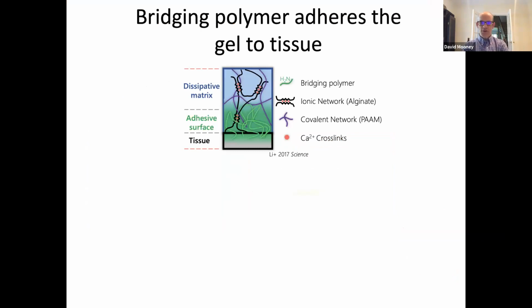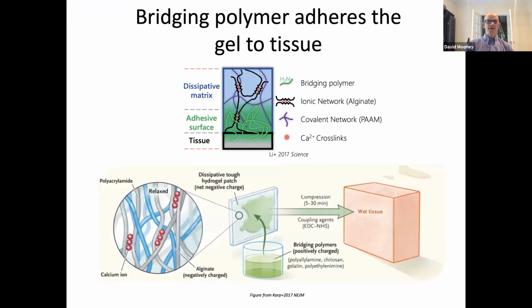And the approach he pursued to accomplish this was to use a bridging polymer. In this case, typically we're using chitosan, though we can use a variety of materials. And so the idea is we have the tissue, we have the hydrogel, and then there's going to be this green polymer here that will have physical entanglement with both the hydrogel and the tissue, have electrostatic interactions with both, and also covalent interactions that we mediate via carbodiimide chemistry. So the basic idea is we have the hydrogel, we would coat it with this solution. In essence, you can think of it like a primer.